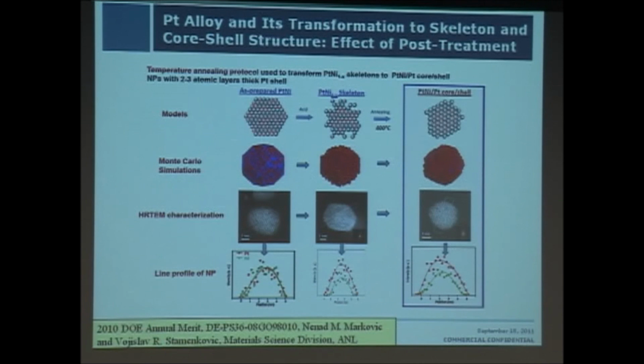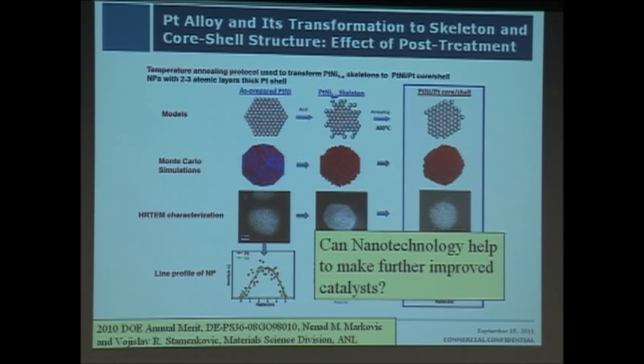Another example is the core-shell structure that people mainly talk about. Initially, when we were working on platinum alloy catalysts, we quickly figured out those alloy catalysts would dissolve in our real-world environment. After that, the dissolution generated what we call a skeleton type of structure. Although the top surface looks more platinum-like and more stable, when you expose those areas to the outside, the stability is still not good. So when you continue to treat them, you may be able to generate a real core-shell structure, as evidenced by those characterizations, and you can get better performance.